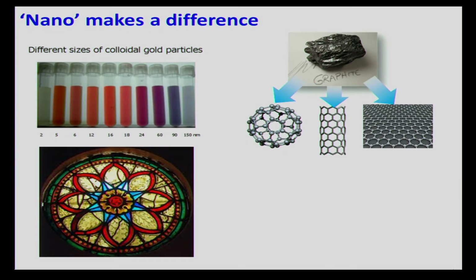So coming to diamond, or coming to carbon materials, what happens if you shrink the size of them? Well, besides diamond, the other family of carbon material that's very well known is graphite. And when you shrink the size of graphite, you have all kinds of interesting materials. You have this closed shell fullerene. When you have a single layer of carbon, you can either lay them out and have a graphene, or you can roll them up to have carbon nanotubes. And these have really very, very different properties from their bulk counterpart, the graphite, for example.